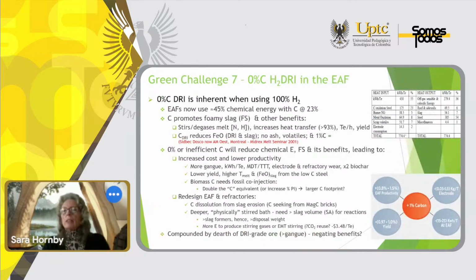Number 7 challenge is the zero carbon hydrogen DRI in the EAF. Zero carbon is inherent in 100% DRI, but 100% hydrogen use in the DRI plants. Currently, electric arc furnaces use about 45% chemical energy, and that's what the chart shows over here, with 23% of that energy coming from carbon oxidation. As I said earlier, carbon promotes the foamy slag, and it has other benefits because the CO bubbles that form stir and degas the melt, and they increase the heat transfer up to over 93%, increasing tons per hour and yield. Carbon in the DRI also reduces the FeO that's inherent in the DRI and also in the steel slag.